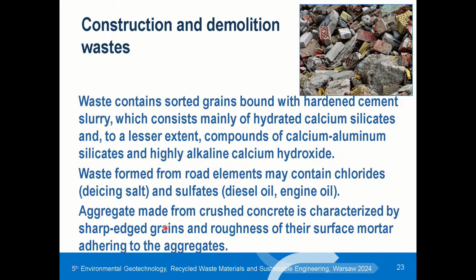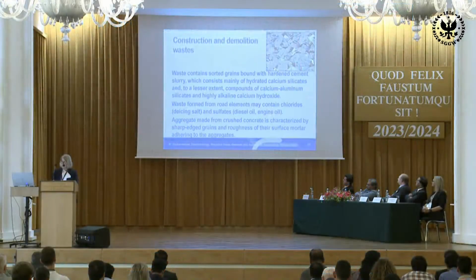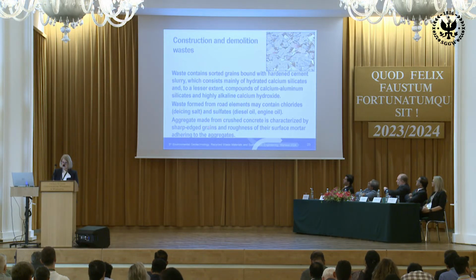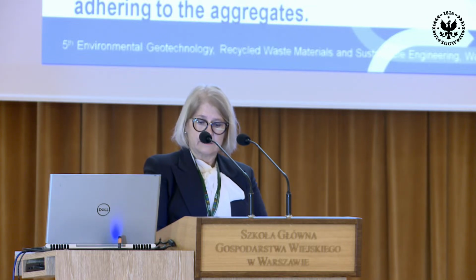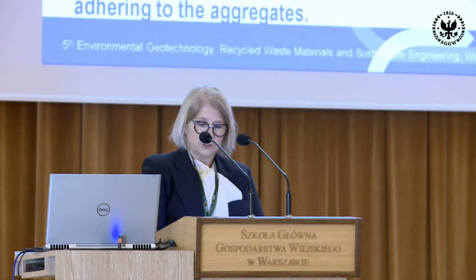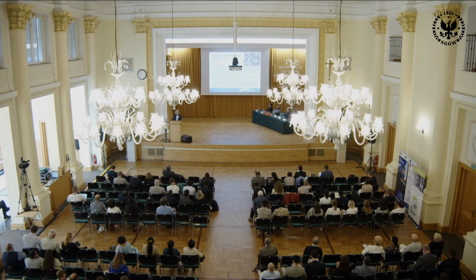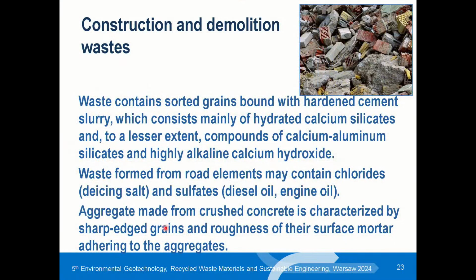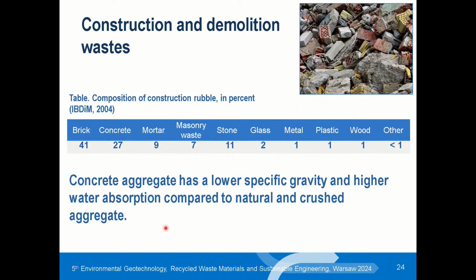The last group is construction and demolition waste. Waste contains sorted grains bound with hardened cement slurry, which consists mainly of hydrated calcium silicate, and waste from road elements may contain chlorides and sulfates from diesel oil and engine oil. Aggregate made from crushed concrete is characterized by sharp-edged grains and roughness of the surface mortar adhering to the aggregates. In the table, we have a composition of the construction rubble in percent, and we can see that brick and concrete are the main waste in this group.